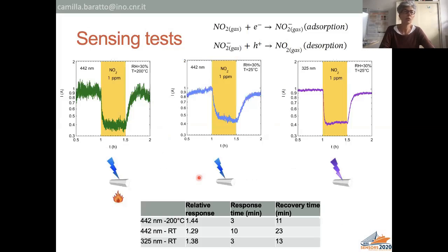For sensing, we put NO2 coming from certified bottles inside the test chamber, and we checked the following condition: 200 degrees C plus blue light. Here you have a nice curve, just blue light over the nanowire, and UV light. And from here to here, you have almost a small decrease in the relative response, but a big increase in the response and recovery time.